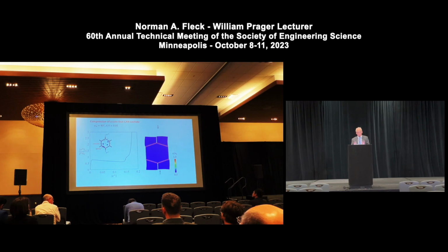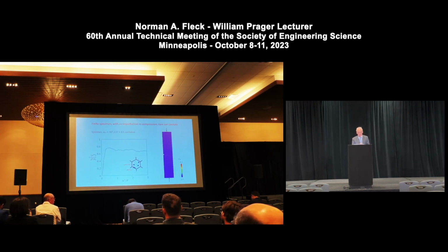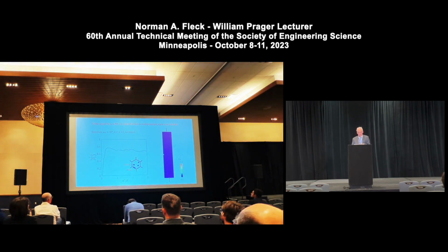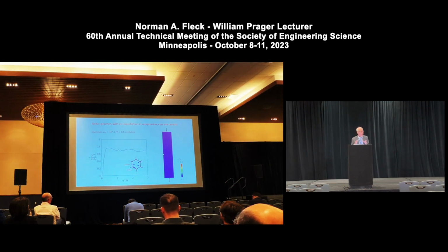It can increase in volume, but once the volume comes back to the initial value, lockup takes place, and the structure is much different. So this filled lattice is behaving initially as open cell, but once the volume goes back to the initial value, lockup takes place, and it then deforms as a constant volume lattice. So there's this important aspect of physics, which is that whether cavitation takes place or not in a core has a major effect on the strength. If you think of an experiment where you apply surrounding hydrostatic pressure that's large enough, then you will switch off this cavitation mechanism.